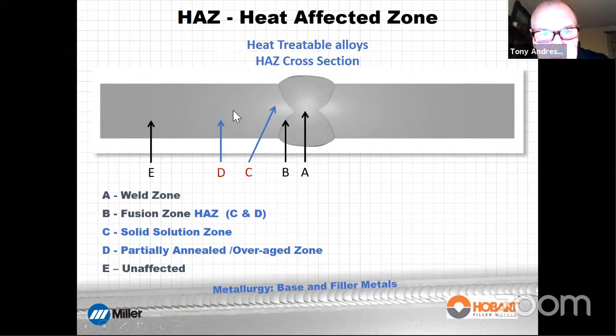That's a fallacy. Some people tell you you've got to preheat it. That's nonsense. The only purpose preheat serves, as far as I'm concerned, is to draw away moisture, because it certainly doesn't help with regard to heat sink. You need high current density to do that. So yeah, that's one of the issues we have with welding the heat treatable alloys.